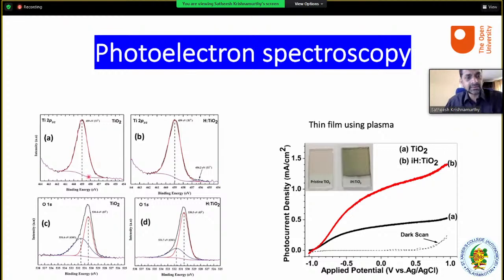If you look at what happens there, this is called the line shape of the spectrum, and this line shape determines how the bell curve looks, like this bell curve. The photo absorption is taking place at the surface, and then the electrons are released and we collect the released electrons. These energy electrons go and undergo inelastic scattering, so we collect them. When we collect them, in the doped and undoped samples, you can see the doped sample in terms of hydrogen.